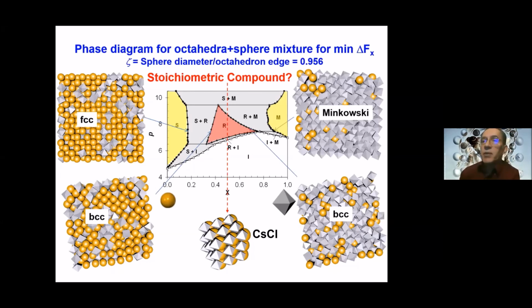And so as you start mapping this coexistence, you start sort of discovering the phase diagram. And at some point, you will see that all of a sudden, we went from having, say, this coexistence to this other coexistence, where the system changes from being the isotropic phase into becoming this R phase. And likewise, you do it from the other side. And a good confirmation is that the results from the integration coming from one end or the other should agree. And so in our simulation, we make sure that that's the case. But this R phase, we didn't know about it, it just appeared as we were doing our thermodynamic integration.